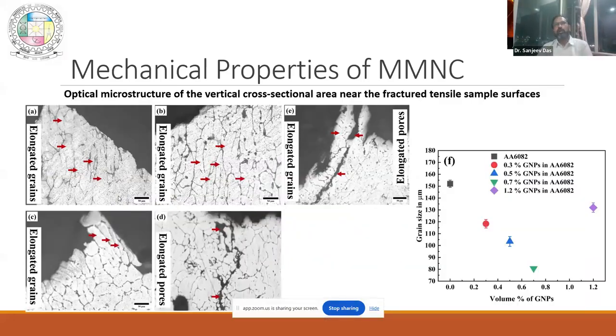Now, when you are doing any fracture surface analysis, don't always look at the fracture surface. You always check what is beneath that fracture surface. So we take a section of the fracture surface and we see what is going on there. We saw a lot of elongated grains for all the composites. That means there is some amount of elongation. That means that nanoparticles are not resisting the elongation, meaning it is allowing the material to elongate. However, they are basically failing. And that was again interesting.